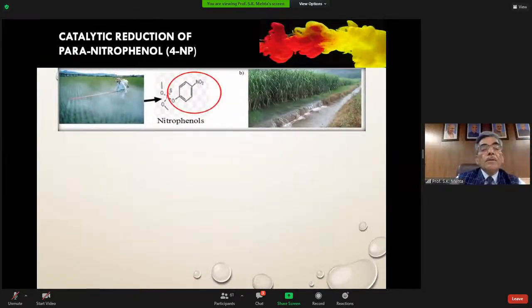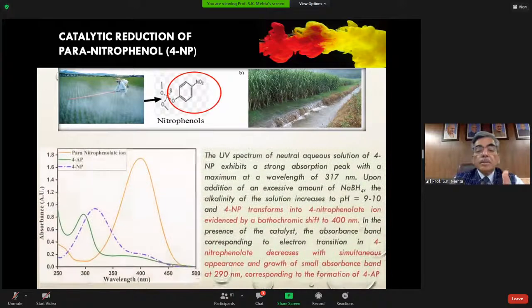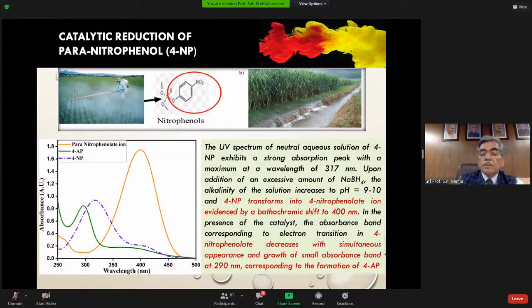Then we use this, very briefly I'll tell, for the catalytic reduction of para-nitrophenol, because this is a reaction which is tried by many people when they produce some product. So you can see that 4-nitrophenol transforms into 4-nitrophenolate, as one can see in the shift of the peaks. And this reaction was very, very successful using the molybdenum-based starbon material which we have produced.